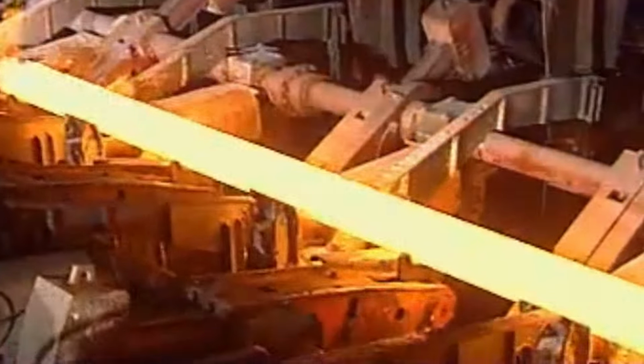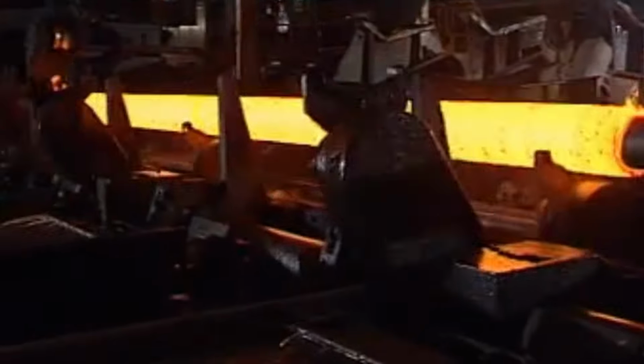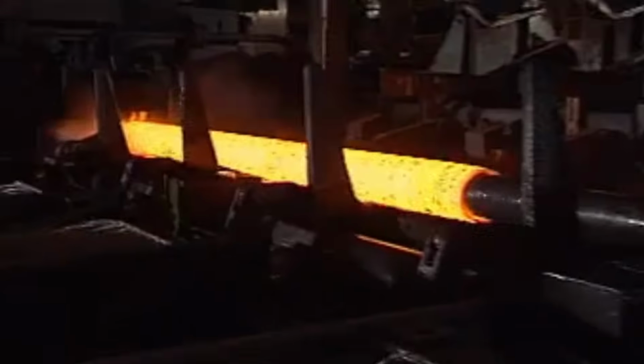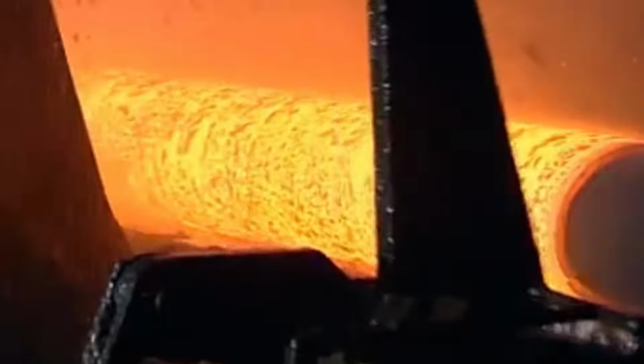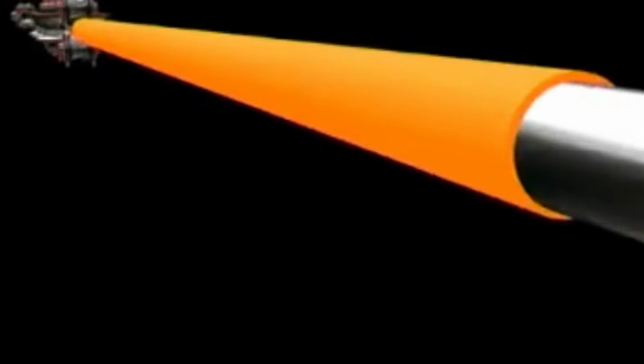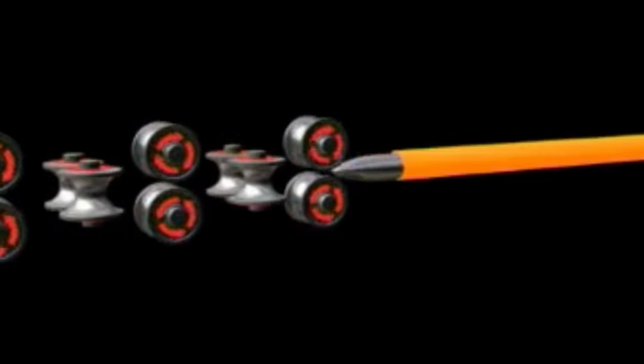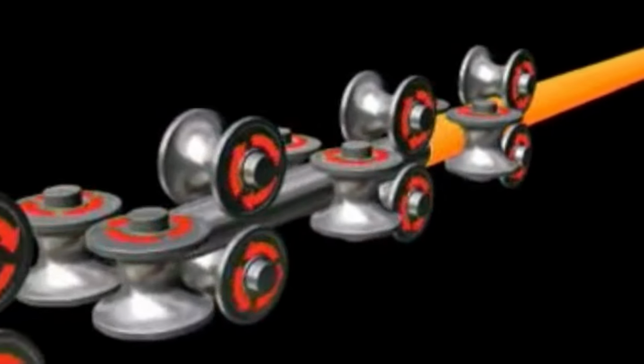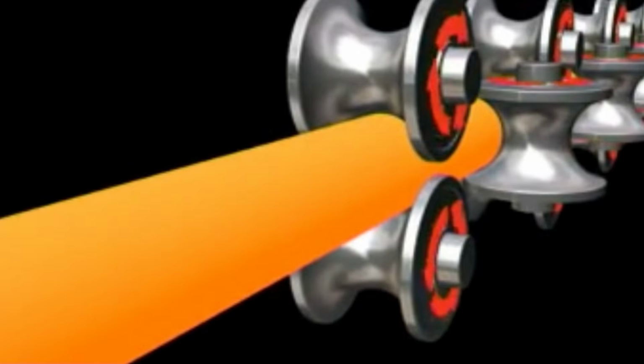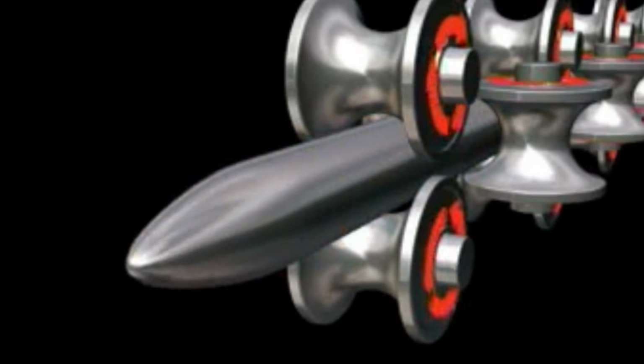This intermediate product then continues to the second rolling stage. A mandrel is inserted to support and size the internal diameter, while the hollow shell passes through several pairs of rolls that progressively reduce the wall thickness. Process accuracy is ensured by continuous online measurement of wall thickness, taken around the tube at multiple longitudinal positions to guarantee uniform wall thickness.